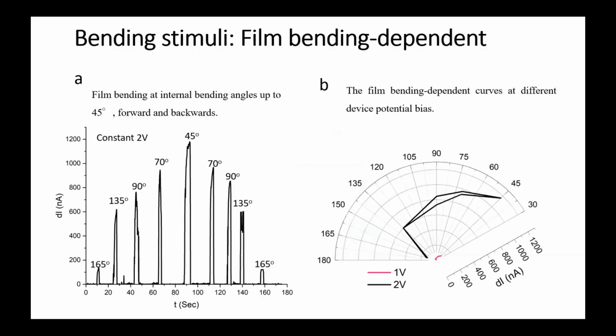The last is the bending stimulus. When we bend the film, we take the angle from 45 to 165 degrees. If we bend it, we measure the angle inside of the film. When we bend at 45 degrees, we see the highest response, and as we can see in this plot, in comparison between 1 volt and 2 volt, 2 volt gives us the highest response.